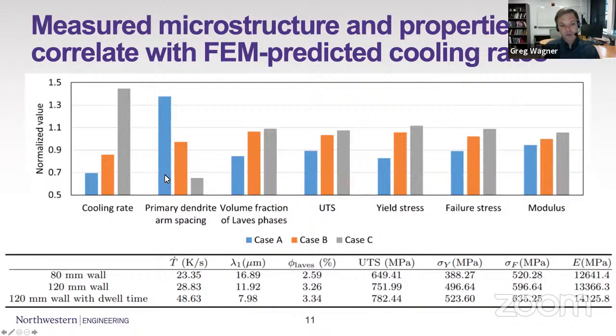The dendrite arm spacing decreases across those. And then there's a resulting change in the material properties for each of those different microstructures. So the strength in particular goes up as the microstructure gets smaller, which again is fairly well expected. So that's great. We can use our temperature histories in order to back out a cooling rate and say something at least about the expected microstructure and properties.